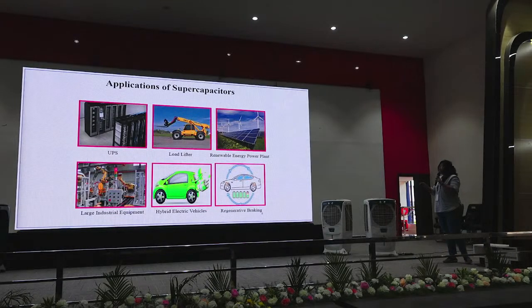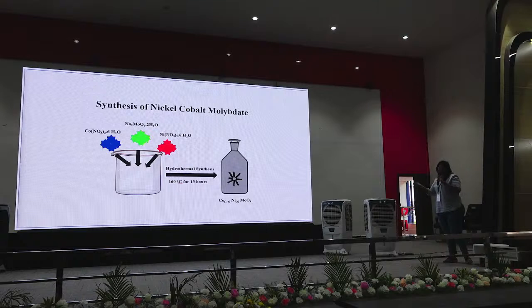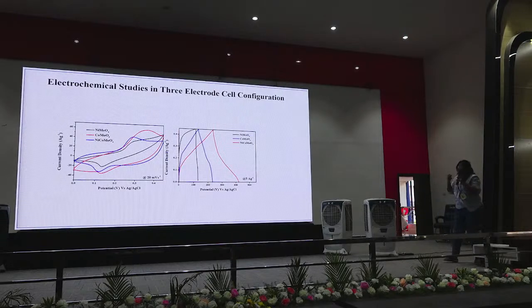So I move on to synthesis and electrochemical characterization. This is the basic synthesis. My novelty is not on the material side, but on the electrochemical studies and prototype fabrication. This is the normal hydrothermal synthesis I have done, with different nickel ratios in cobalt molybdate. I missed annealing, so that is one part I have left out. Coming to the electrochemical studies, I did both two-electrode and three-electrode studies. I synthesized nickel molybdate, cobalt molybdate and nickel cobalt molybdate. I impregnated different percentages of nickel into cobalt molybdate.